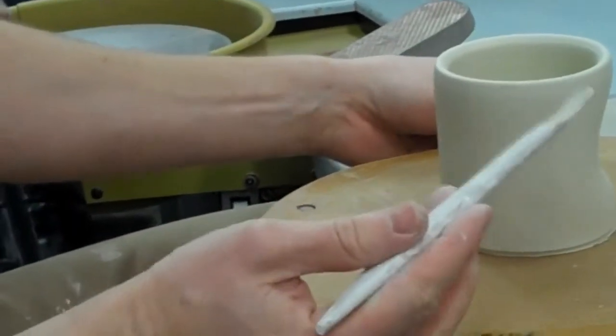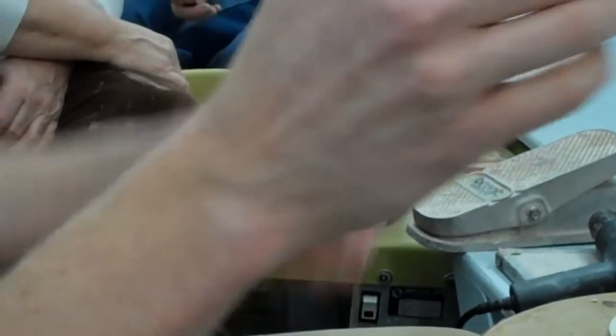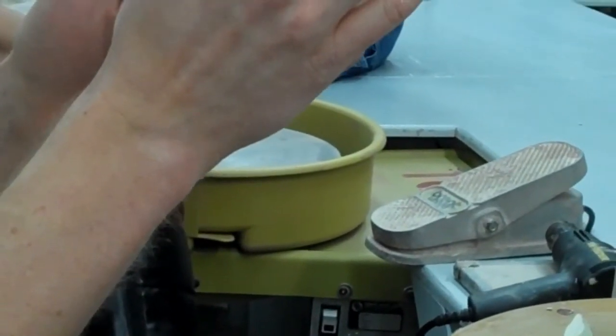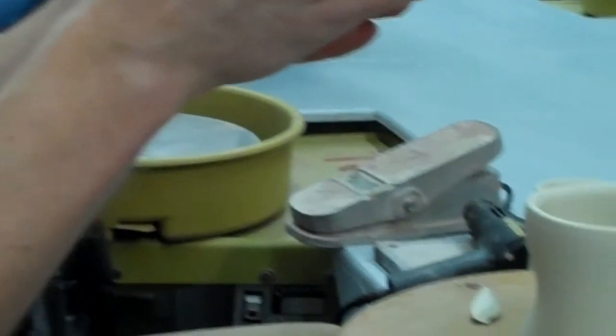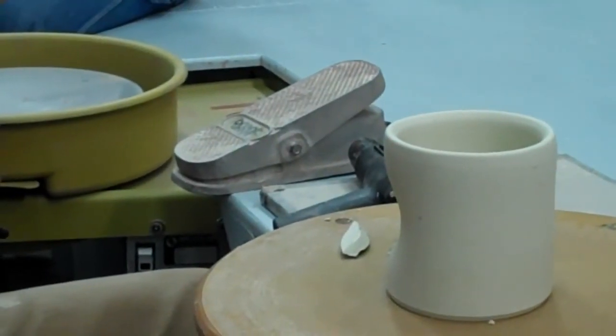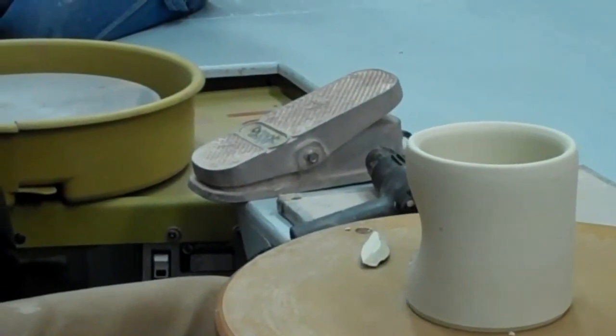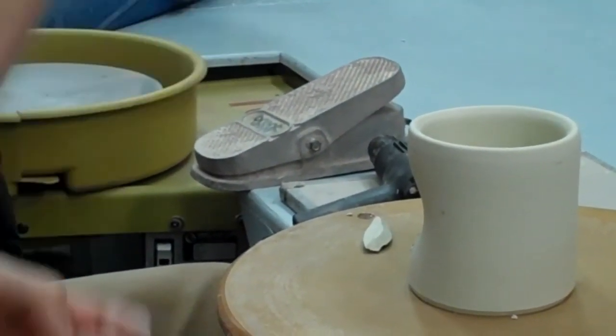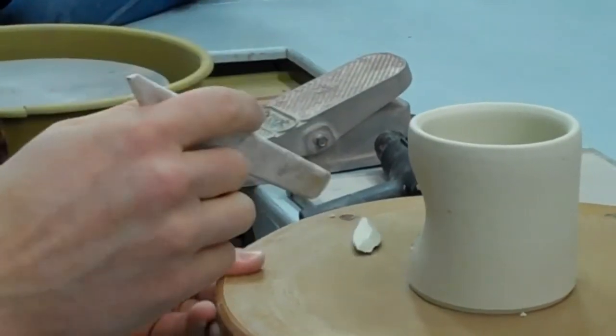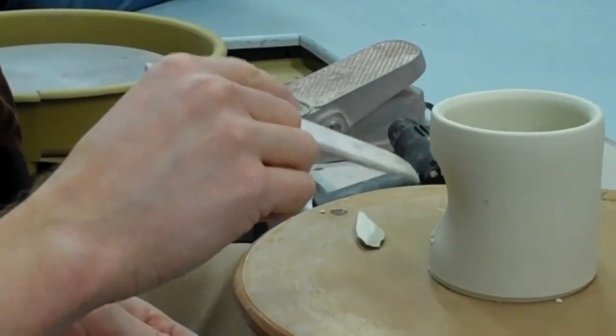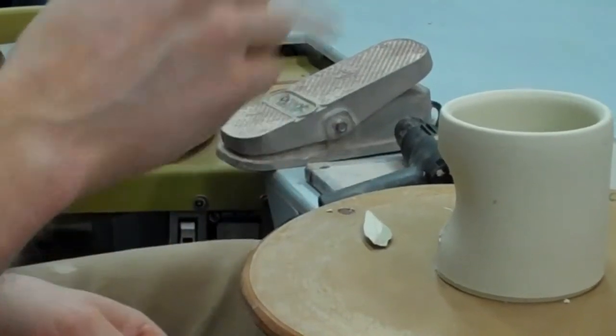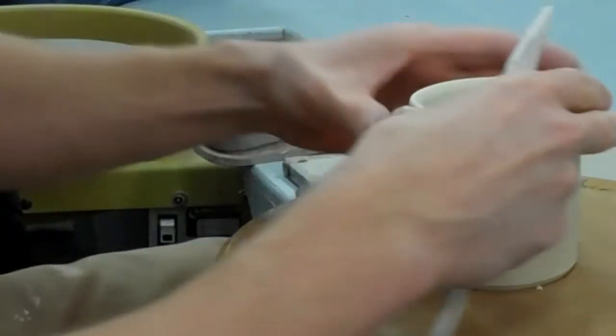That's why I do the bevel. If I was to push that straight cut together instead of beveling it, a lot of times you won't be able to get that compression and that line will show back up later after you bisque, or you'll even get a crack there. I have never had a cup crack on this line doing it like I'm doing it right now. I'll go back inside and pull that extra clay over the same way.